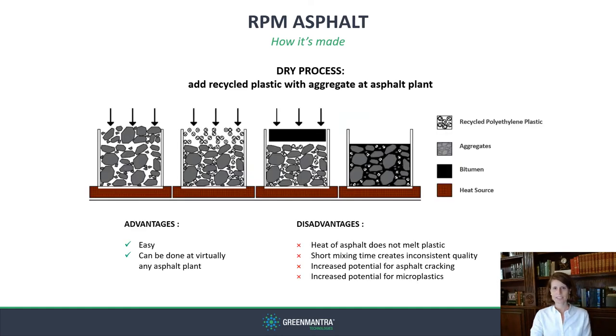The dry process is a technique used widely in India and Southeast Asia, where recycled plastic particles are added at the end of the process together with other aggregates. The advantages of this approach are mainly due to its ease of use. It can be done at virtually any asphalt plant. The disadvantages, however, can be quite significant due to the inconsistent quality that can lead to premature cracking. Additionally, because the plastic particles are not melted or incorporated into the bitumen, they remain suspended in the asphalt, creating an increased risk for microplastic generation at the surface of the asphalt.